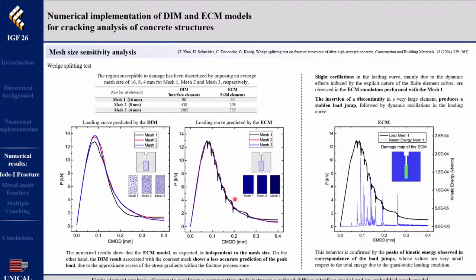To better understand this behavior, that is the load jumps in the ECM simulation, I had also plotted the kinetic energy computed by the ECM model, and it shows peaks of the energy in correspondence of the load jumps due to the dynamic effect induced by the explicit solver. Above all, when very large discontinuities are inserted in the finite element. Yeah, this is very interesting, this last approach that you explained, because eventually you can correct the simulation. Yes. For the DIM, I could reduce the fracture energy employed in the analysis to obtain a right loading curve.